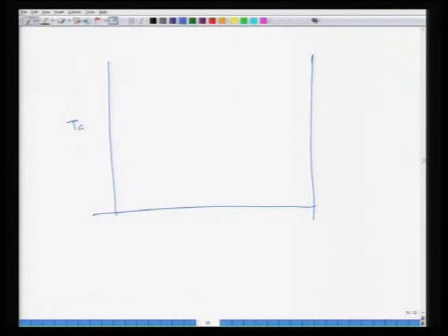So essentially the beauty of this whole phenomenon is the coupling of this electrical phenomenon with a mechanical process such as distortion of the lattice. So this is essentially the theory of superconductivity. And the experimental validation which was done was essentially, you have Tc versus 1 divided by root of M, and this was done for mercury, for instance, and mercury followed a sort of straight line.